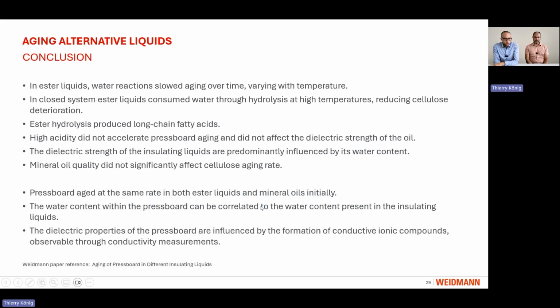So the conclusion of this experiment: in the ester liquids, the water reaction slowed the aging over time. It was depending on the temperature. In the closed system, the ester liquids consumed the water through this hydrolysis, especially at higher temperatures, and reduced the cellulose deterioration. The ester hydrolysis, on the other hand, produced long-chain fatty acids, but no accelerated pressboard aging was observed in this experiment due to this acidity content, and also no effect of this acid number on the electric strength of the liquids.